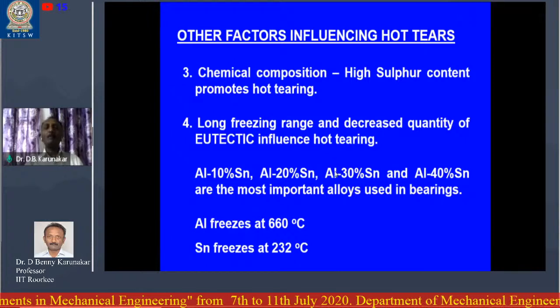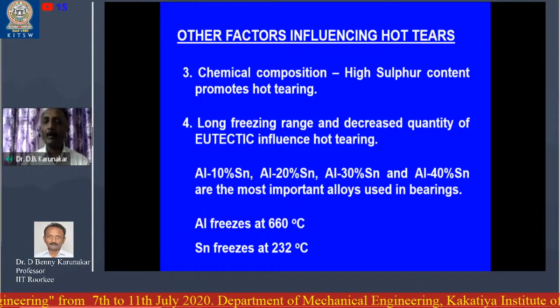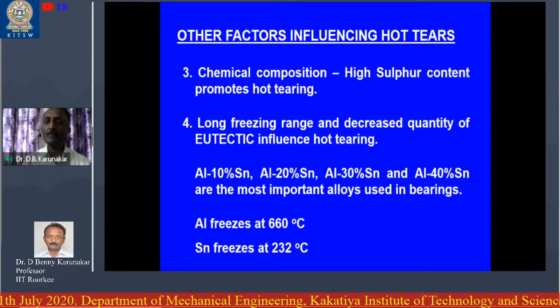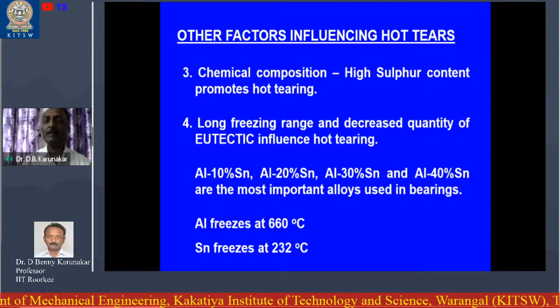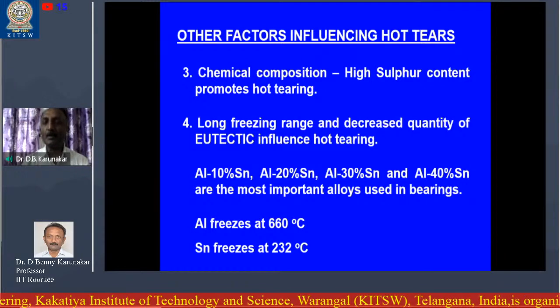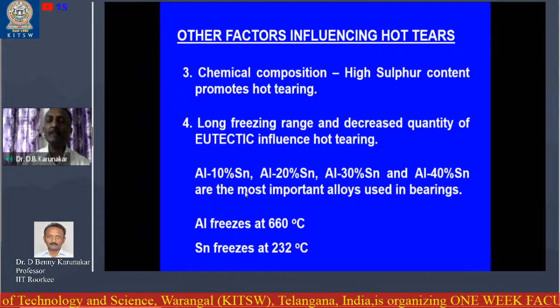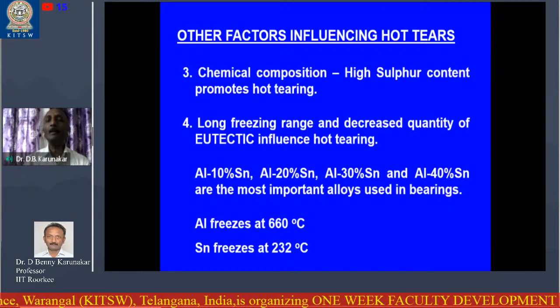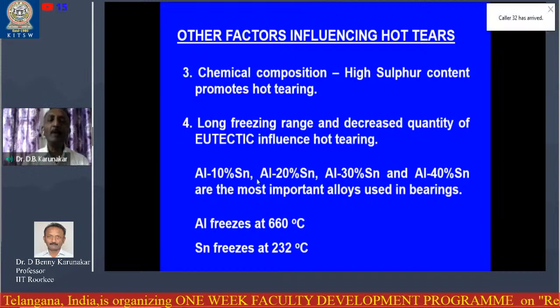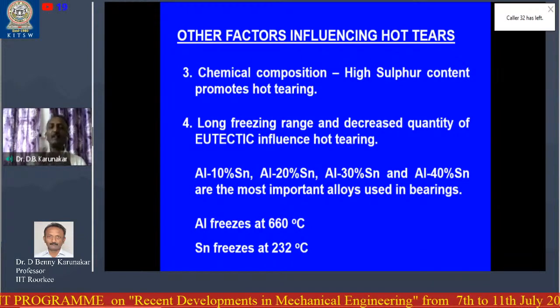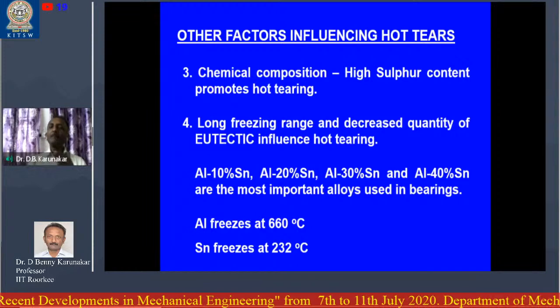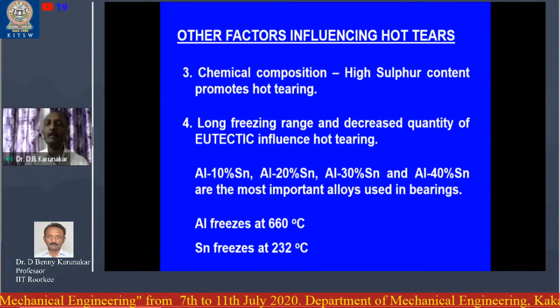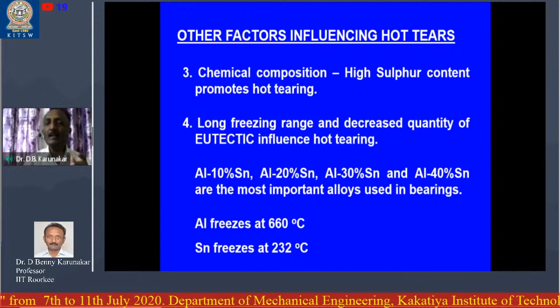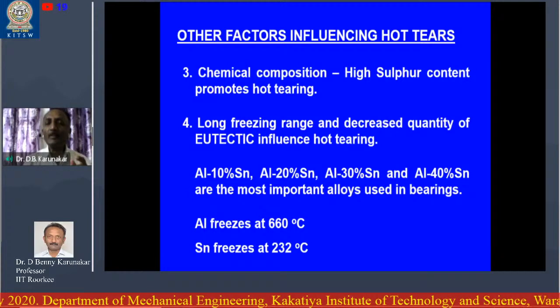Long freezing range, for example, say aluminum. What is its melting or freezing temperature? 660 degrees centigrade. What about tin? 232 degrees centigrade. So what if you take an alloy of aluminum and 10% tin, what about the freezing range? The freezing for aluminum starts at 660 degrees centigrade, and for tin it starts at 232 degrees centigrade. That means the freezing range is nearly or more than 400 degrees centigrade.